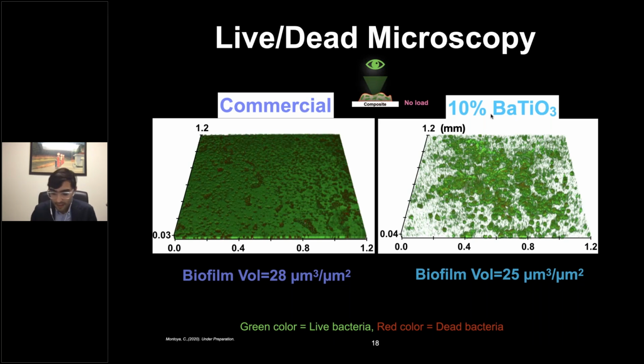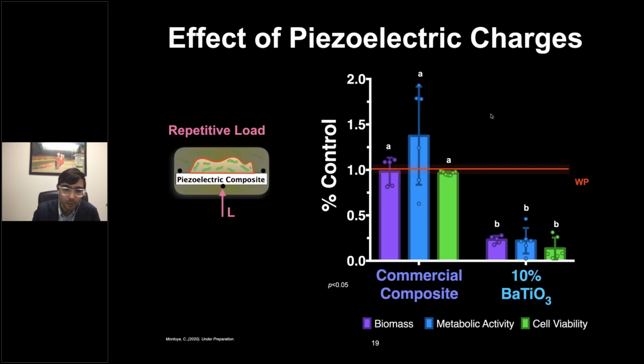If we look for the same features on the 10% BTO composite, the volume of the biofilm is very close, slightly lower, not significant. But we begin to see isolated areas compared to the commercial, and it's a little bit thicker. Somewhat the bacteria was able to form and colonize, but not as evenly and nicely as the commercial, which was quite an interesting result.